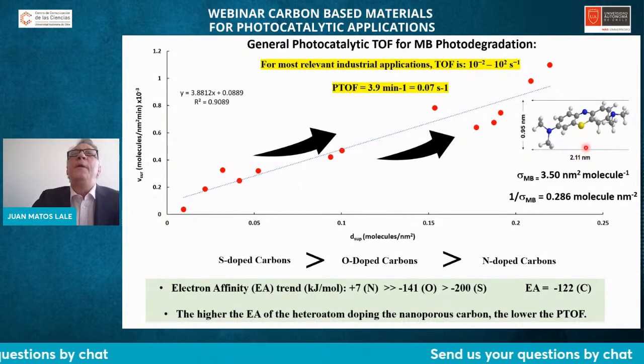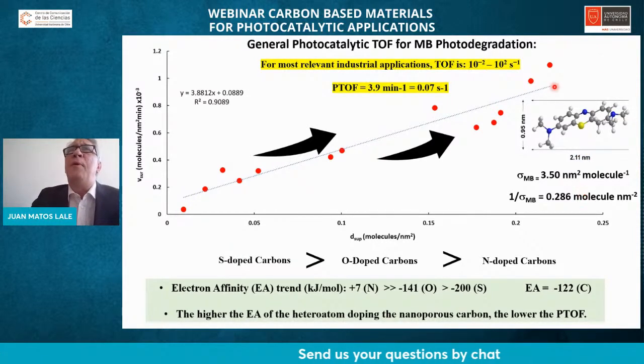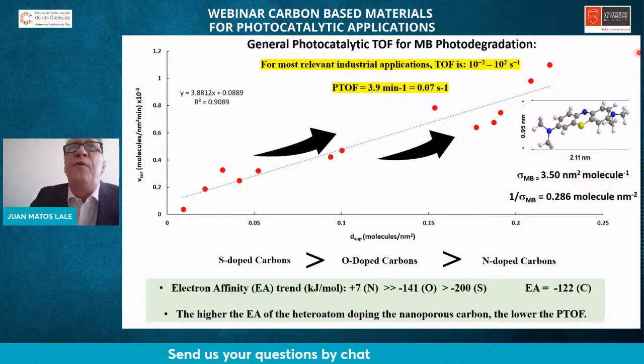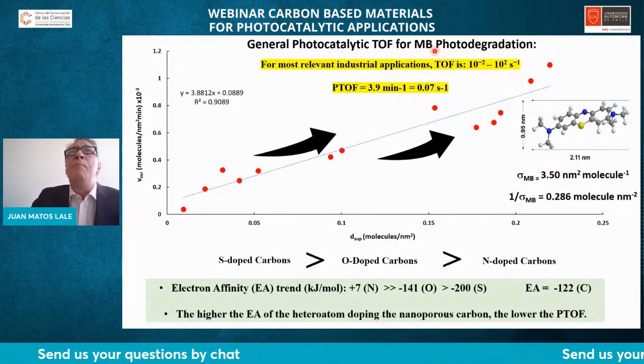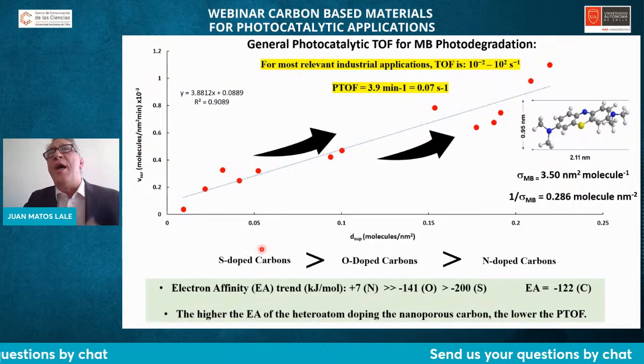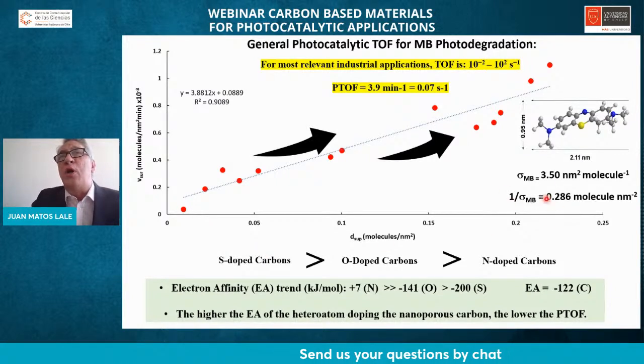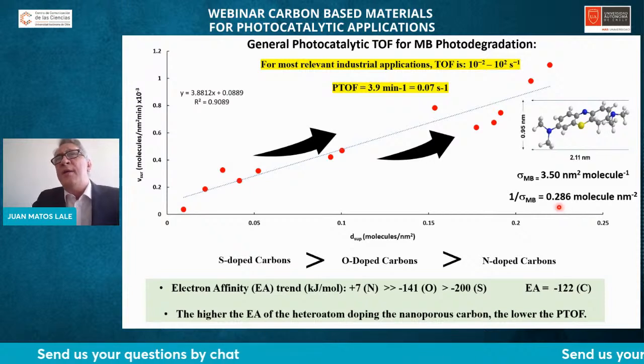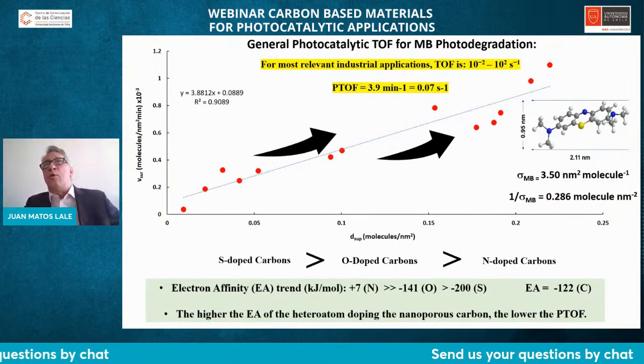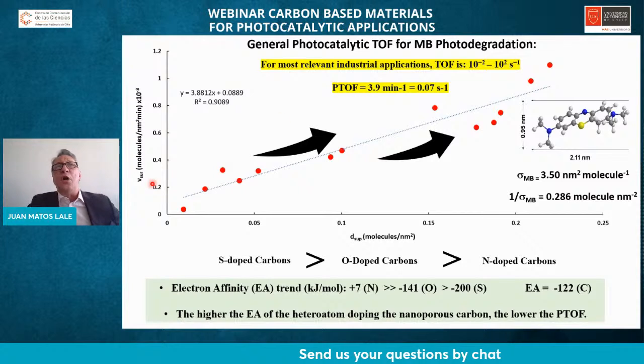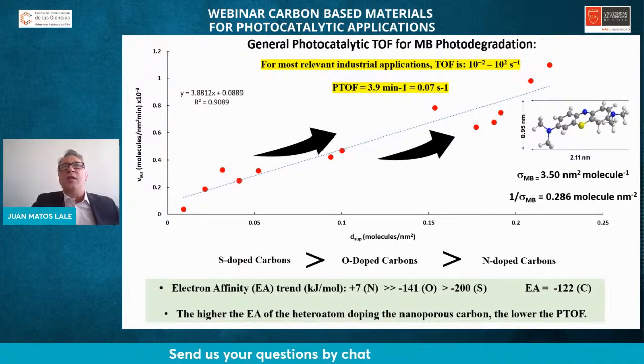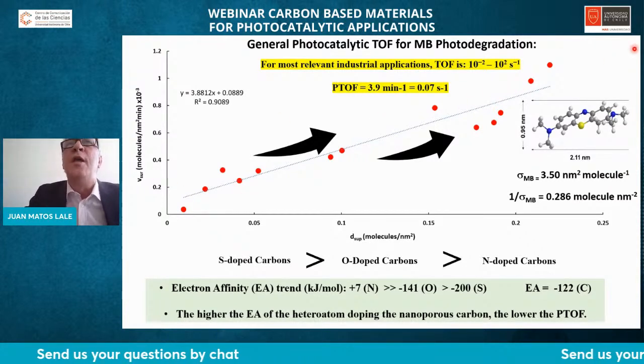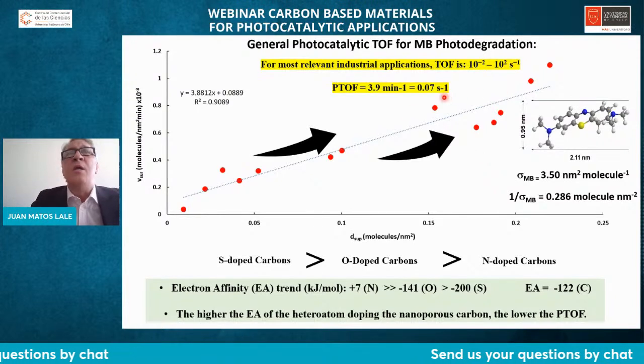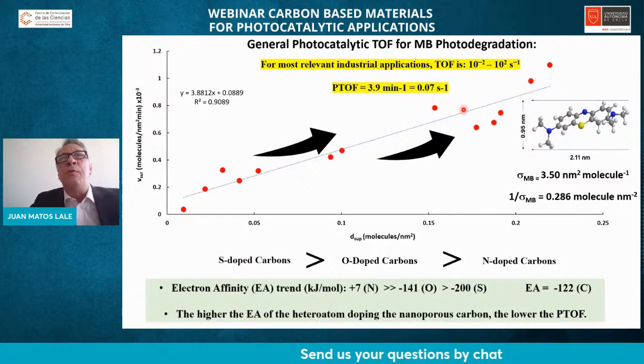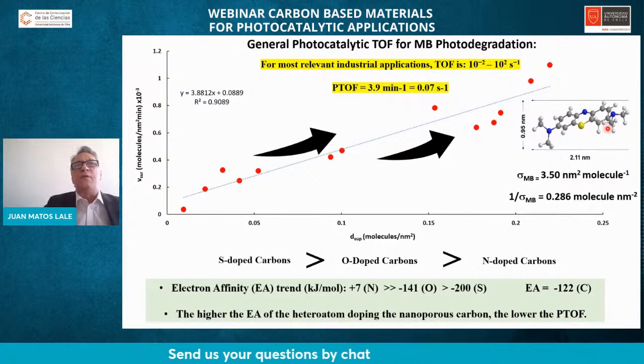Okay, so in addition, we know that we have not achieved the maximum for the methylene blue photodegradation. Why do we know that? Because the reciprocal of the cross-sectional area of the methylene blue is around 0.29 molecules per square nanometer. It could be over here. So this reaction is not at the maximum position. It means that we can achieve even better P-TOF in real industrial application for the degradation of this molecule.